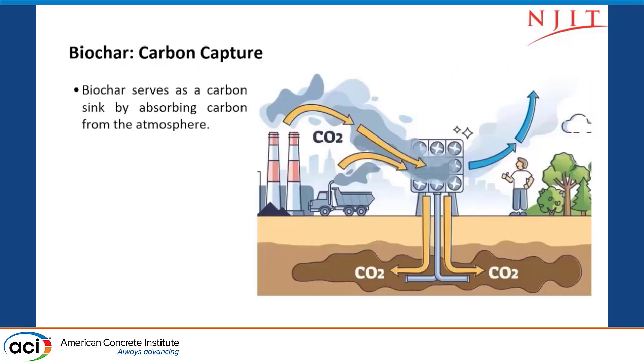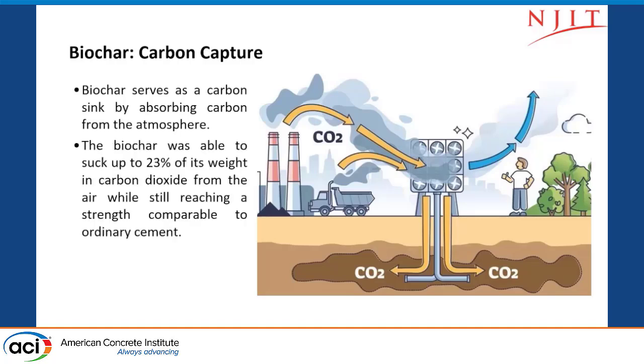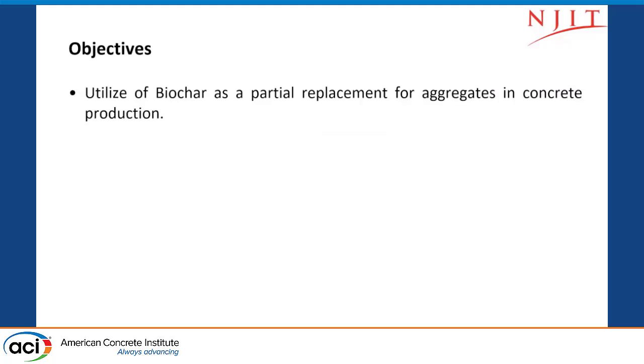And then for carbon capture, biochar serves as a carbon sink by absorbing carbon from the atmosphere and putting it underground. It was able to suck 23% of its weight in carbon dioxide from the air while still reaching a strength comparable to ordinary cement. Then we are going to move to the concrete. Since I am a concrete guy, what are we doing with the biochar, adding it to the concrete? What is the effect of that?